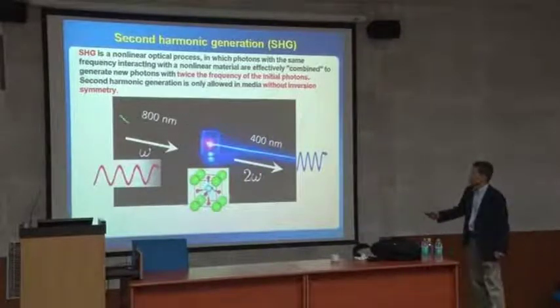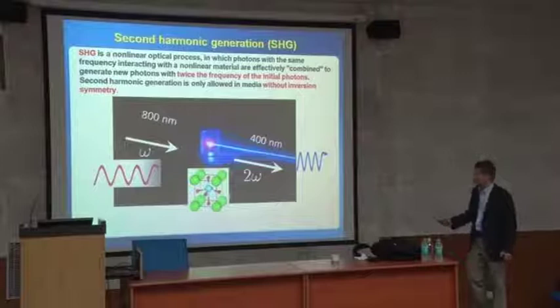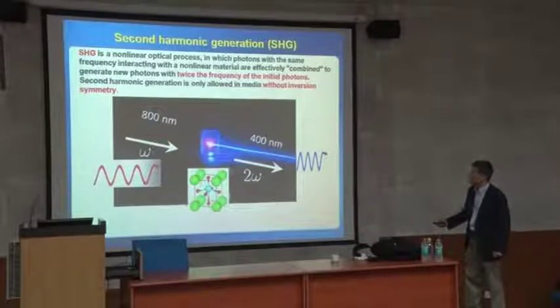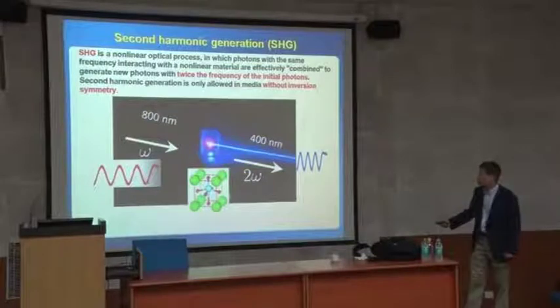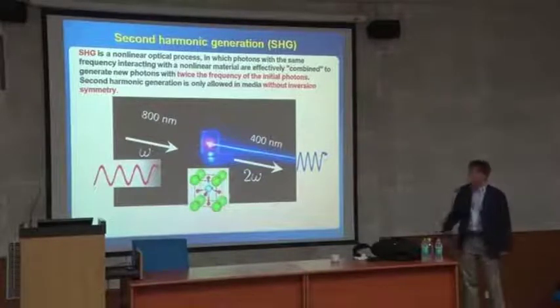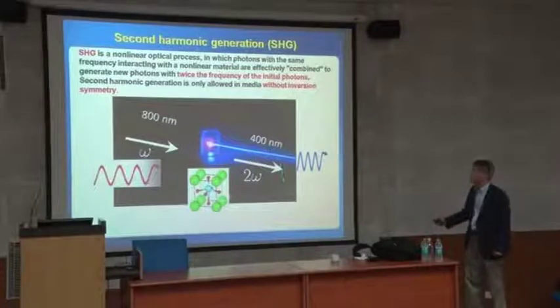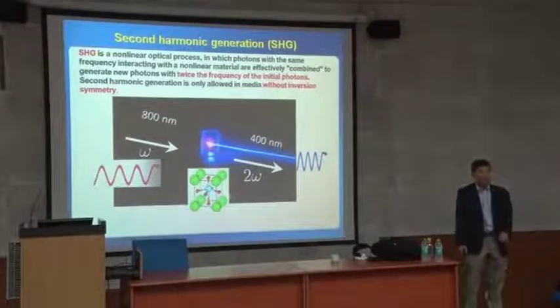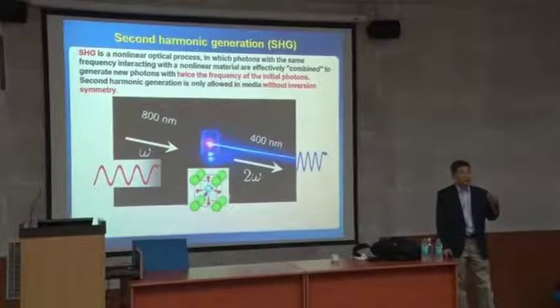So 800 nanometer red light generates 400 nanometer blue. And if you have a material that is non-centrosymmetric, where the atom is not at the center, then this happens, and the signal is finite. But if it is centrosymmetric, this doesn't happen and the signal is zero. So that's one way you can tell polar from non-polar. You simply shine a laser and measure whether the half wavelength is there or not.